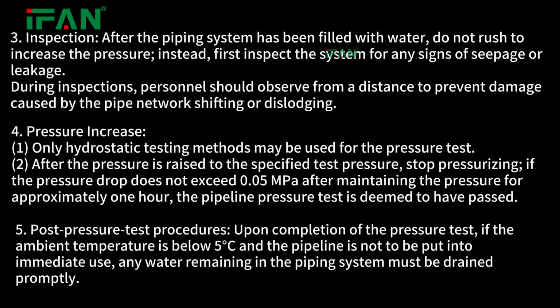2. After the pressure is raised to the specified test pressure, stop pressurizing. If the pressure drop does not exceed 0.05 megapascal after maintaining the pressure for approximately 1 hour, the pipeline pressure test is deemed to have passed. 5. Post-pressure test procedures. Upon completion of the pressure test, if the ambient temperature is below 5 C and the pipeline is not to be put into immediate use, any water remaining in the piping system must be drained promptly.